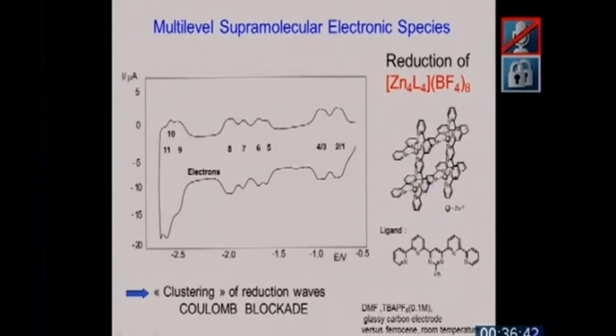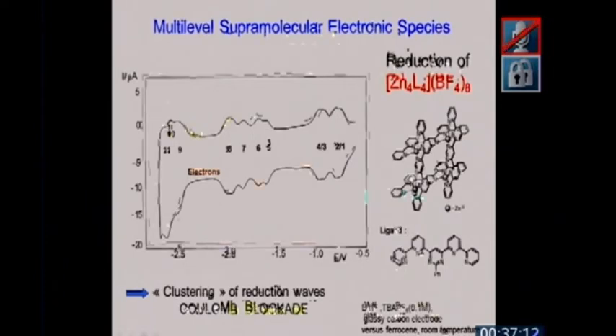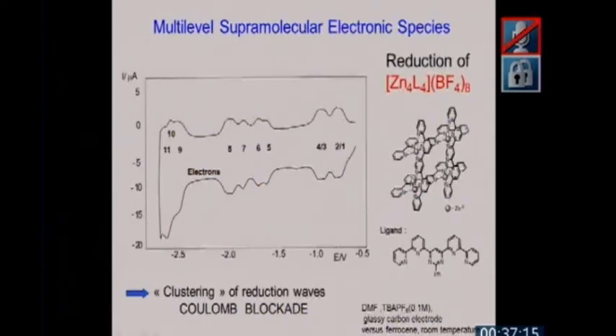Adding another electron is now quite difficult because of Coulombic repulsion between electrons. So you have now to push with the potential by about half a volt, and now you can inject 5, 6, 7, 8. At this stage, the system is now neutral. You have 8 electrons and 8 positive charges. You can, of course, inject more electrons, but then it becomes very difficult. So what I wanted to show here is that this system behaves quite normally. And the difference in these potentials here can also be called the Coulombic blockade, where because of Coulombic repulsion, adding a 5th, 6th, 7th, 8th electron becomes more and more difficult compared to 1, 2, 3, 4.